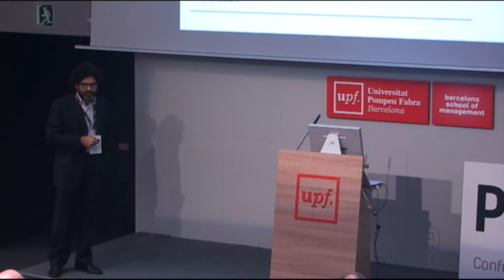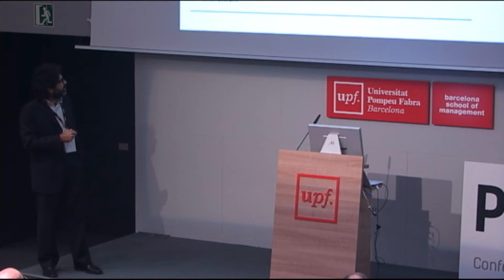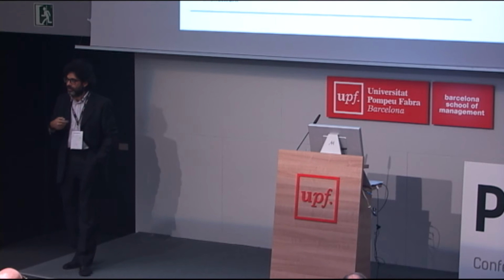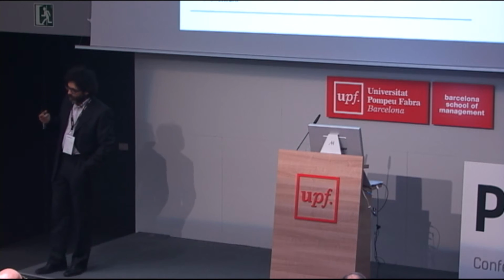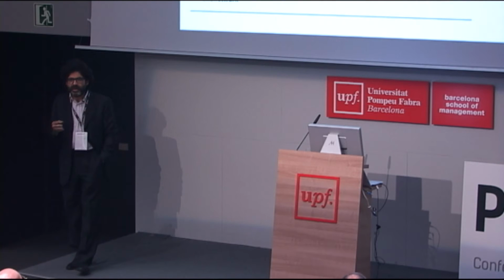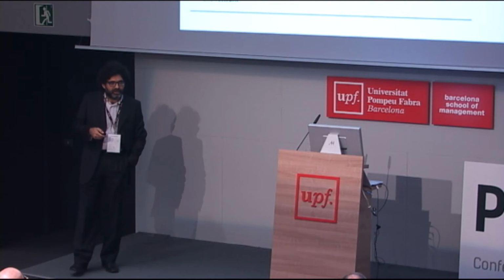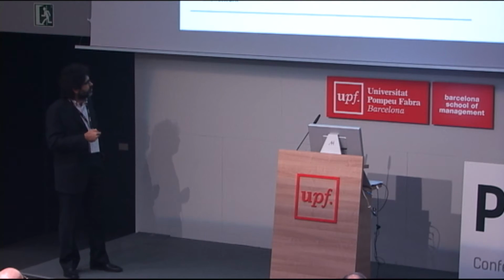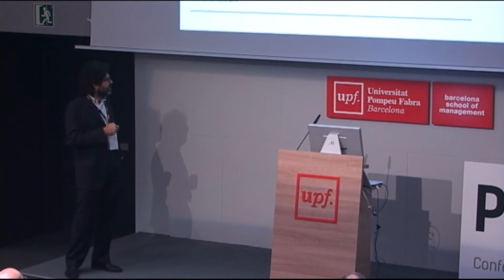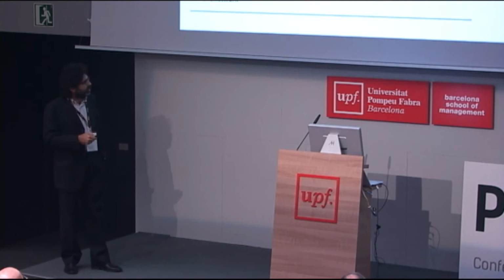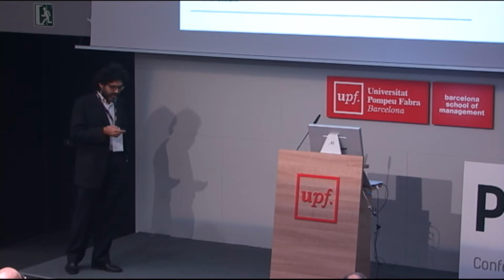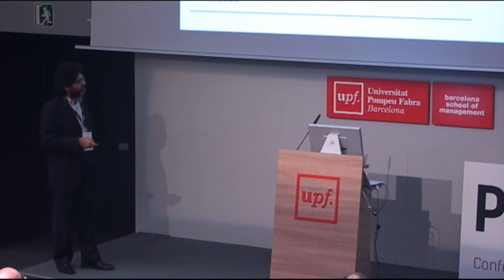We started as a proof of concept with nanowires of length around 1.5 microns, while in this kind of cell the optimum thickness is around 10 to 15 microns, but the result was pretty clear. In fact, Professor Wang a few years later got around 7% efficiency with the same concept, but increasing the thickness of the nanowire layer.